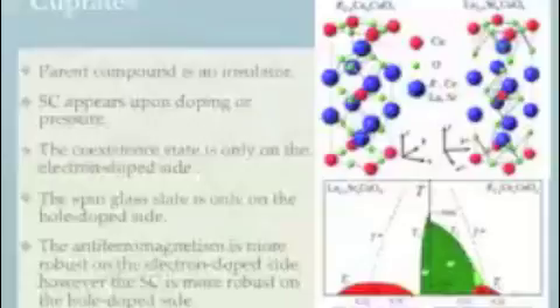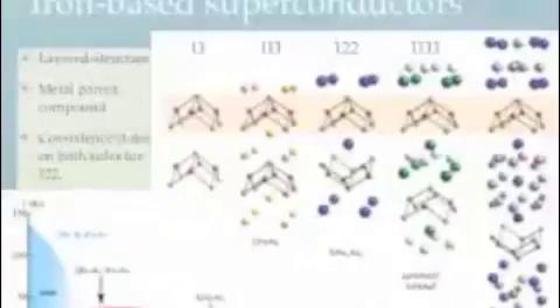Now let's look at the situation in the iron-based superconductors. The superconductors in pnictides have a lot in common with the cuprates. They all have two-dimensional structure, and like the cuprates, the superconducting current only flows on the iron arsenic layers. Like the cuprates, there are different crystal structures for the iron-based materials. They have different structures, and we can divide them into 5 different subgroups by their chemical structures. Different structures have different properties.